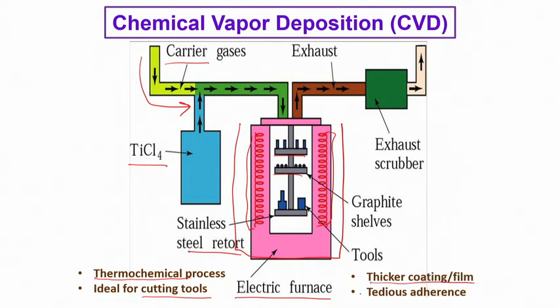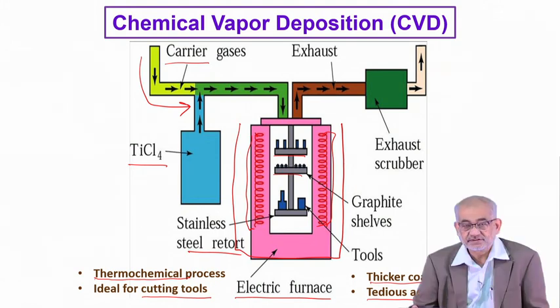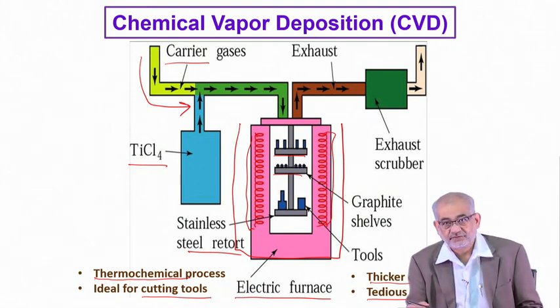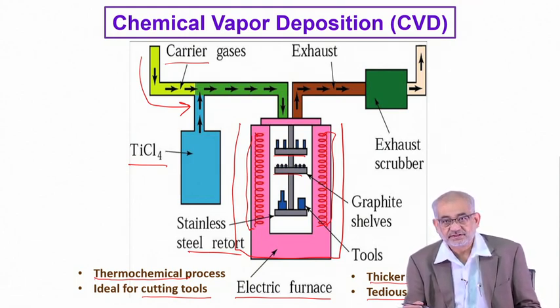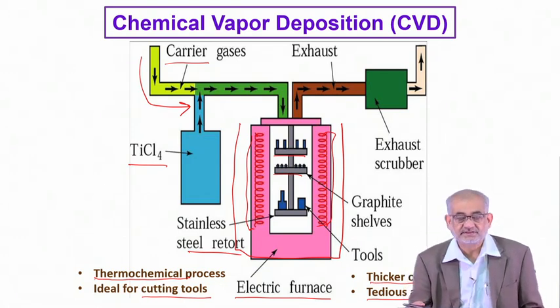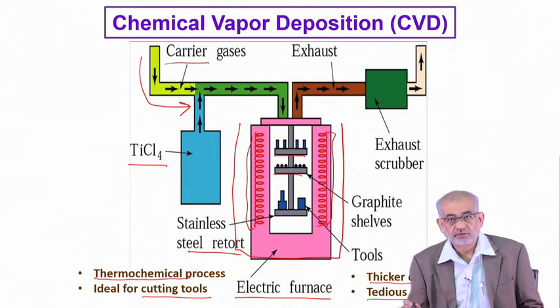What is very important in case of CVD compared to PVD is that the coating or film we develop is fairly adherent. This is because a chemical reaction takes place, and when the film forms onto the substrate, a certain amount of interdiffusion due to the high temperature takes place. There could also be a thin reaction layer, as a result of which the wettability and adherence is better than in PVD or sputtering situations where the interface is always very sharp.